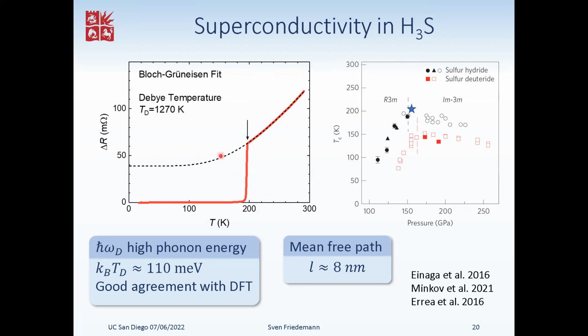Now we can again look at the normal state behavior of this, and again fit this with Bloch-Grüneisen. Here we find the standard exponent of 5 and a Debye temperature of the order of 1300 Kelvin, which is in surprisingly good agreement with the characteristic phonon frequencies calculated from the Eliashberg function. Now you'd say that it's probably acoustic phonons that dominate the electrical resistance, and optical phonons will have a large role in the superconductivity. But nevertheless, this fit is suggesting that the Debye frequency is quite high.